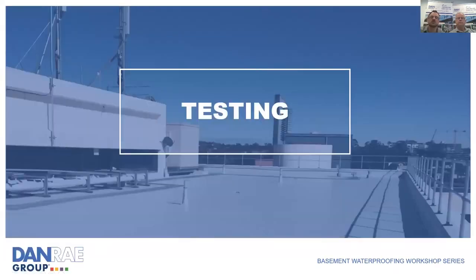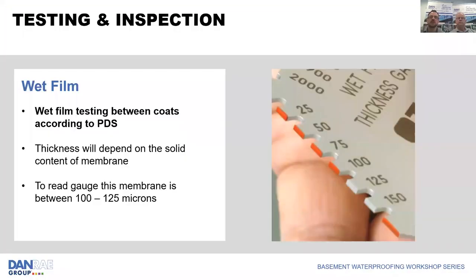So some examples of testing during the installation. During install, very common in waterproofing is wet film thickness. This would be used on a liquid membrane on a basement. All the measurements and what you would expect to get out of a membrane would be on the product data sheet. So the applicator should be installing every coat at a certain thickness.